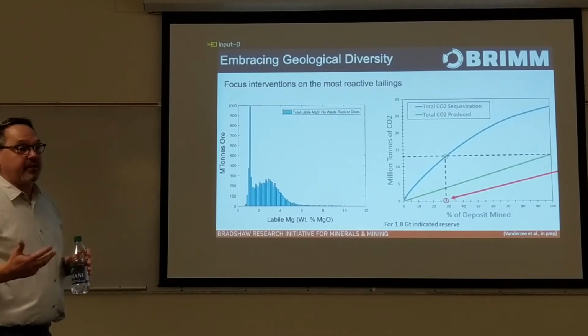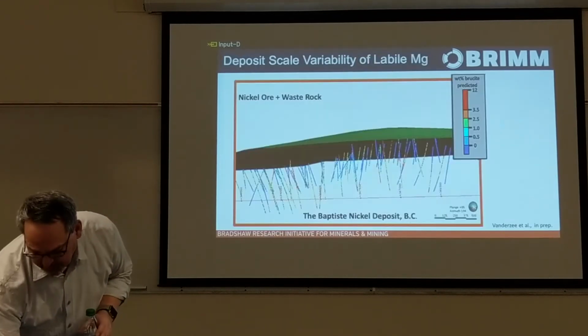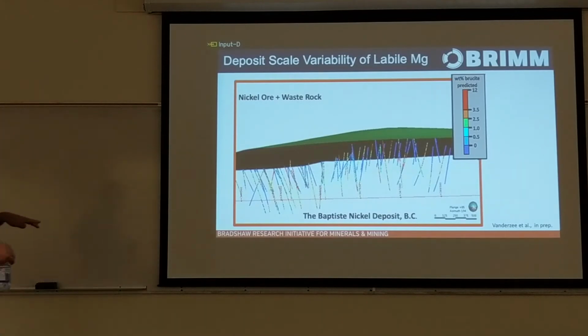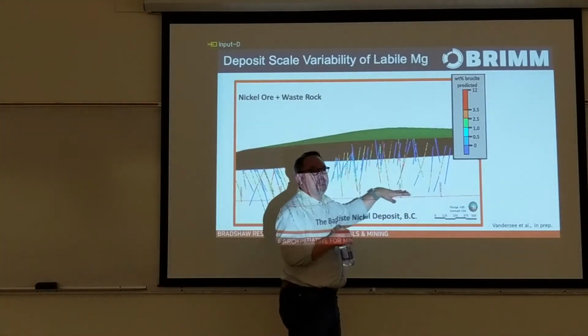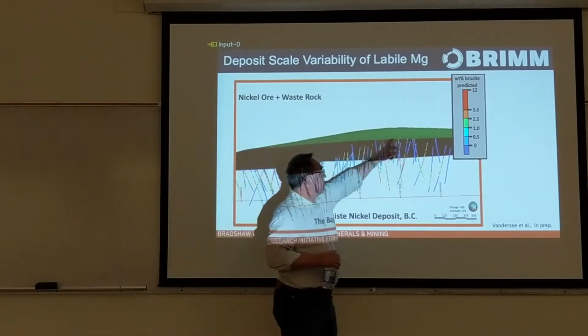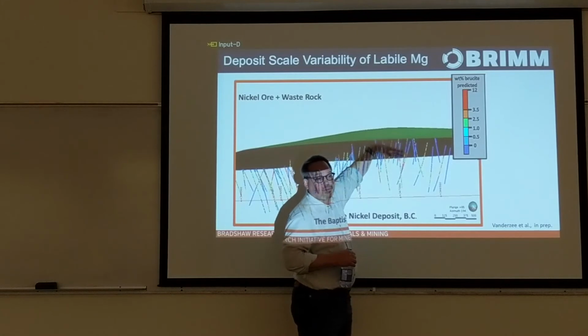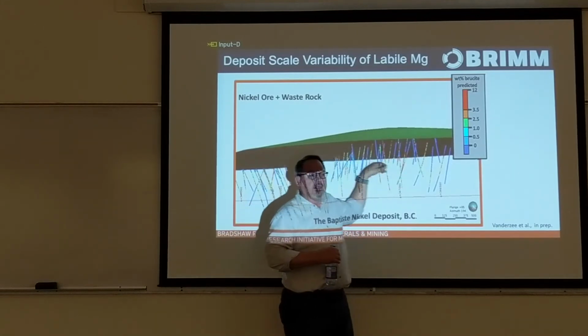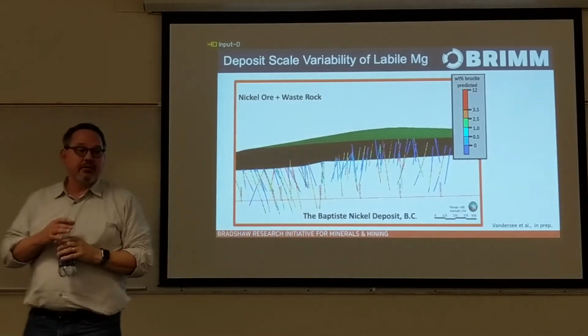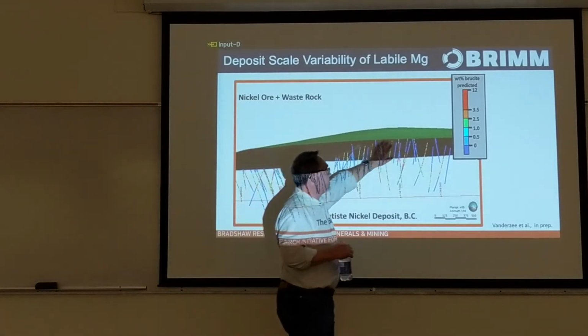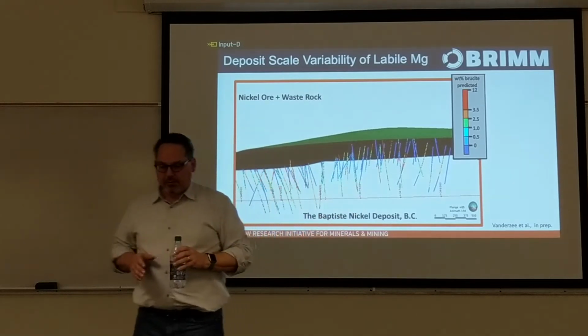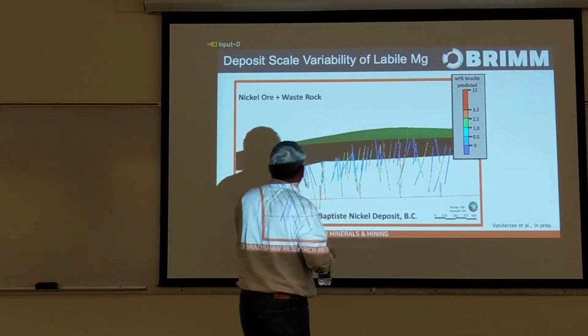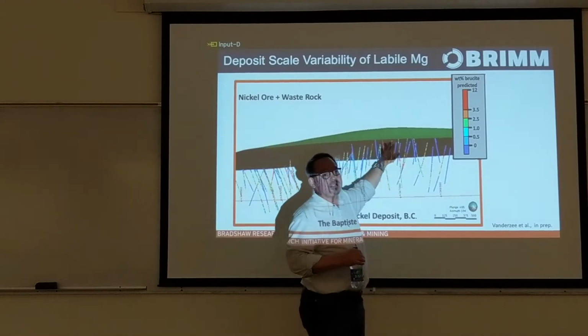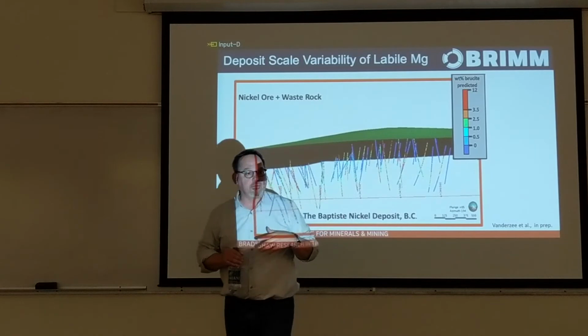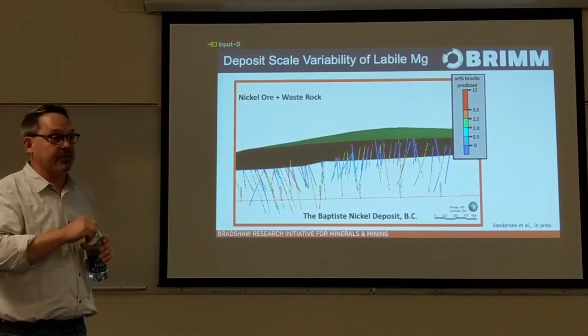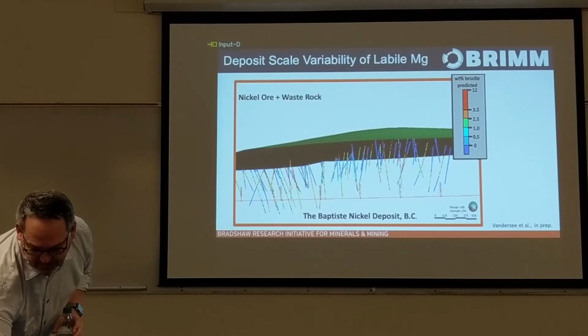But these geochemical data, they're from exploration, so they actually have a spatial component as well. So we can build a three-dimensional model of the labile magnesium content of the ore body and build that into mine planning. And we can recognize areas of the deposit that have high labile magnesium content near the surface. This is stuff that could be captured in the early stages of mining and then treated with CO2 and used for other purposes. In this case, the primary motivation for FPX Nickel, which is the company that has this deposit, is that they want to use this to buttress their tailings dams to enhance the security and stability of their tailings storage. I'll show you some more data on that in a minute.